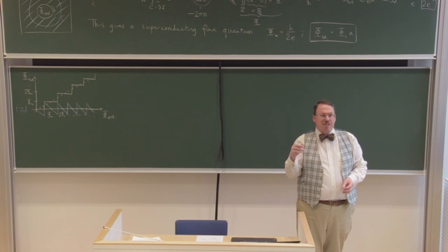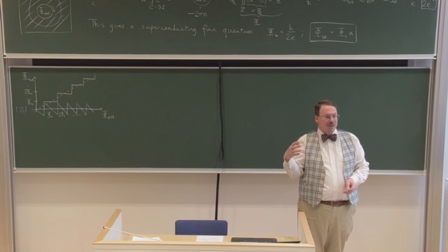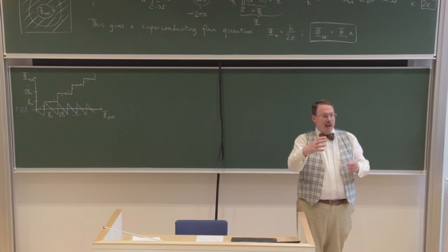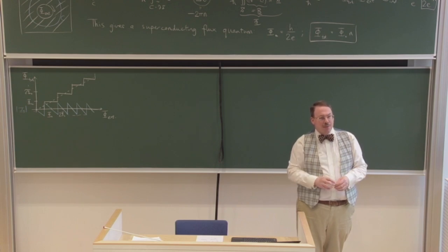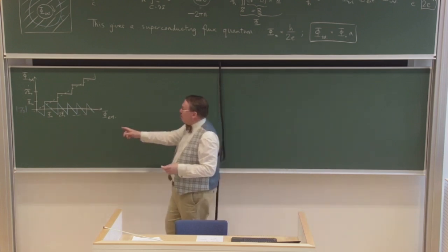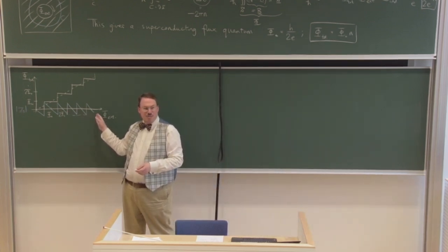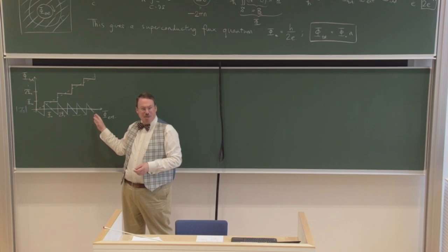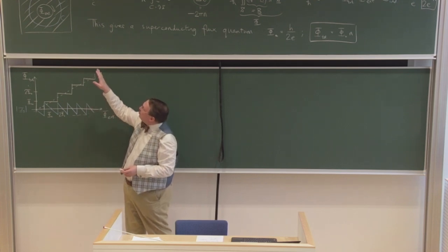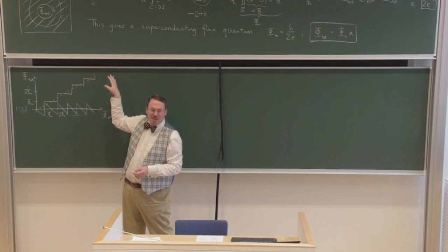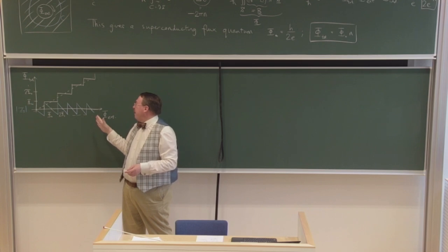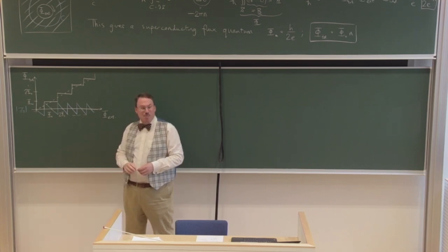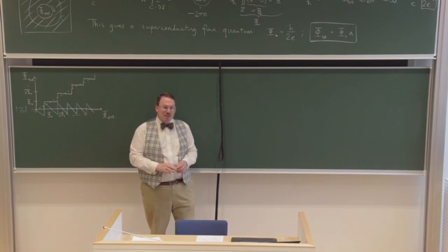But the crucial difference is that this is only sensitive to field changes. So I can have a static configuration with a regular metal where there is a field through the loop, but because it's not changing, no currents are driven. Here I have a static configuration for most of these values where there is a field through the loop and it's running a persistent current. And the field is always screened down to 0 inside the superconductor. So it's different by a power of a time derivative, basically, as lots of the physics of superconductors is.